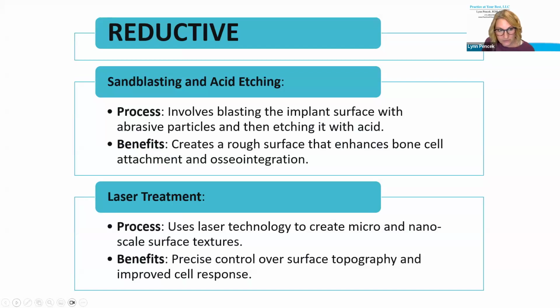So there's two different ways we can do this. It can be reductive. So we have the implant come out of the machine, and now we're trying to create more surface texture. And we can do that with sandblasting. The process involves getting abrasive particles and etching on the outside surface of the implant. The benefit is it creates a nice rough surface that increases the amount of surface texture for the bone and for the blood proteins to attach and integrate with the implant.